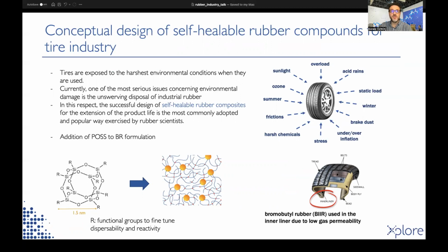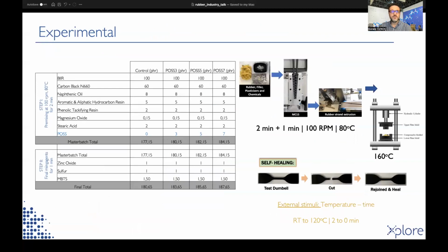The common approach is to use an additive that provides the healing of polymer molecules through physical or covalent bonding of the molecules. In this study, we have also used the same approach, but this time we used a nanocomposite structure having chemical functional groups that can sustain covalent and hydrogen bonding. We have focused on the inner liner compound, which is composed of brominated butyl rubber. We used 3 different POSS compositions ranging from 3 to 7 PHR POSS in the rubber matrix. The mixing was carried out in a high torque microcompounder at ATC. The screw speed was 100 RPM and the total mixing time was 3 minutes.